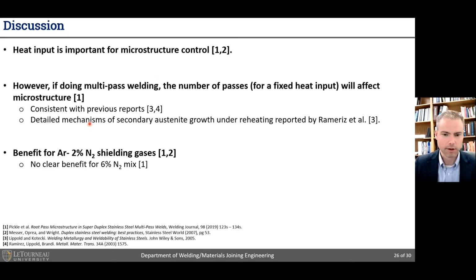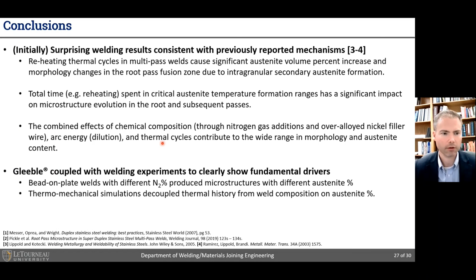And if you really want to dig into the details of the mechanisms of secondary austenite growth, which has been well explored by Ramirez and colleagues in previous work. And then finally, in line with industry practice, clearly the 2% nitrogen shielding gas is acceptable. So to finally conclude, the initially surprising welding results when we dug through all the details were consistent with previously reported mechanisms. It's clear that reheating is driving the secondary austenite volume increase due to the formation of intragranular secondary austenite. Total time spent in this critical 800 to 1200 C temperature range is important for increasing the austenite content.